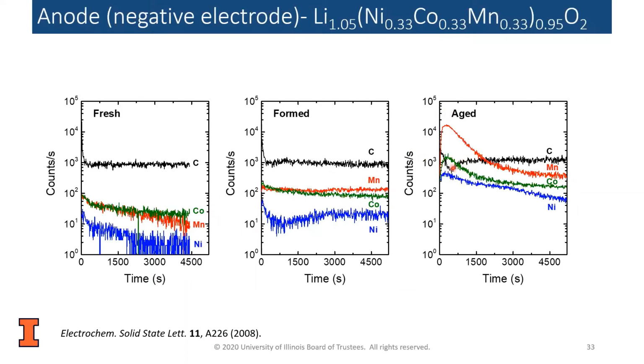And this is not good for the battery in that it is going to stick to the anode's SEI, be trapped there, whereas during the charging cycles, when the lithium is shuttling towards the anode, it's going to pick up the lithium.